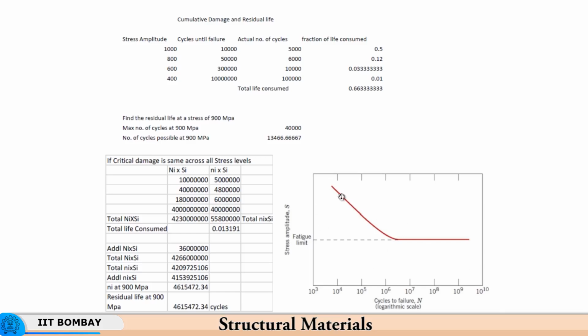Now, if you look at this stress amplitude versus cycles to failure curve, you find that here there is a greater stress, and so as the stress increases the corresponding number of cycles to failure decrease. So, this part is heavily dependent upon the stress, because higher stress has a significant effect on the number of cycles to failure. On the other hand, at this stress there is no effect. The number of cycles to failure can be 10 to the power 7, 8, 9, 10, it does not fail at all. So, what it means is that the material is able to endure the fatigue damage for an infinite period of time.